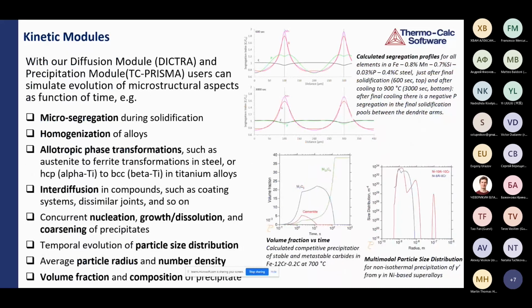Using the kinetic modules, Dictra and TC-Prisma, one can simulate the evolution of microstructural aspects as a function of time. That could be microsegregation during solidification, could be homogenizations, for example, allotropic phase transformations, could be interdiffusion in compounds as if you have a coating system, for example, or dissimilar joints, and so on.